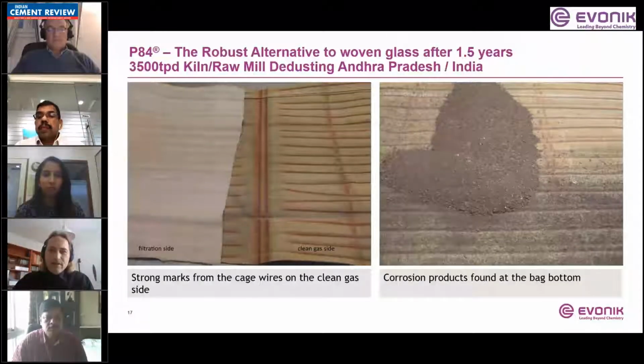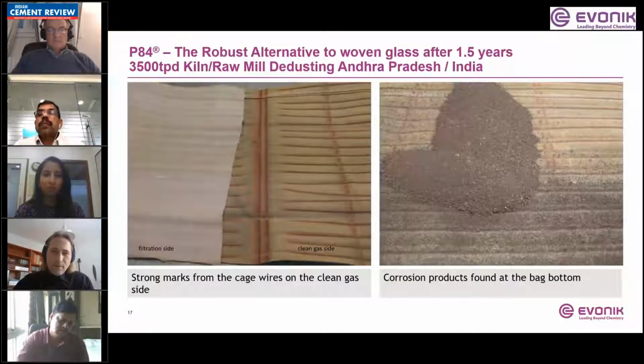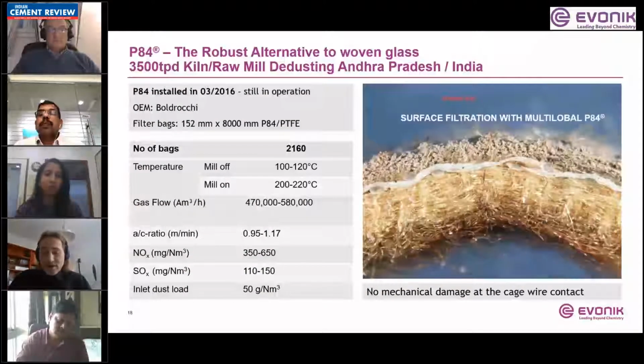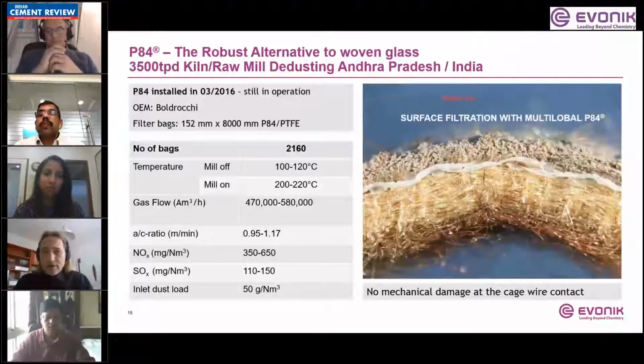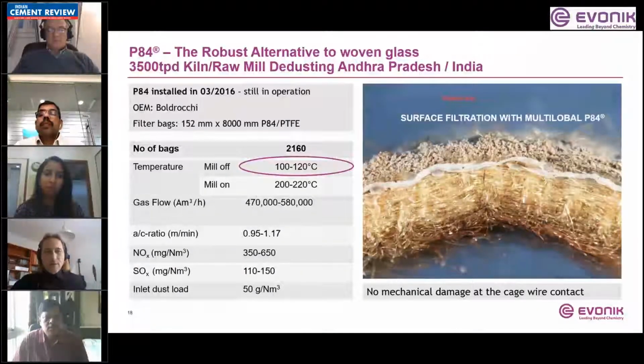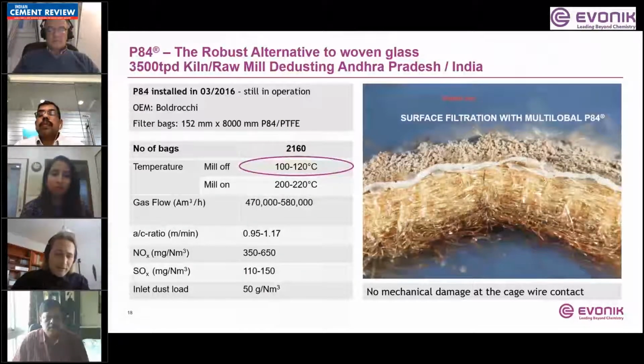So this wear layer can be abraded without any damage to the bag and performance. And this picture shows right at the contact point to the cage wires, there's no corrosion, there's no damage at all. You see just the orange corrosion products on the bottom on the clean gas side and the permanent dust cake on the dust side. The problem in this plant is mainly the low operating temperature in mill off operation, which is just around 100–120 degrees C, which easily leads to condensation and corrosion of the mild steel housing of the baghouse.